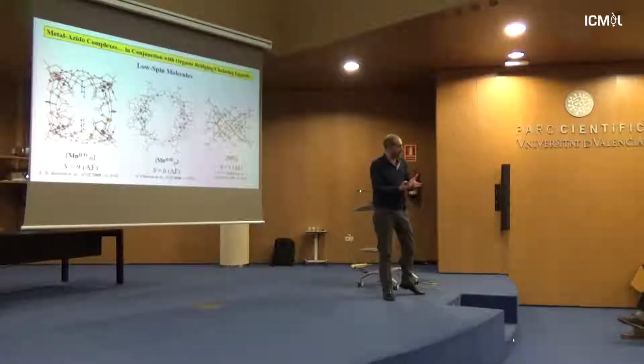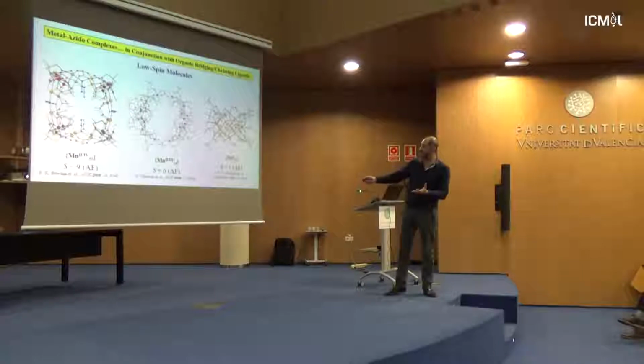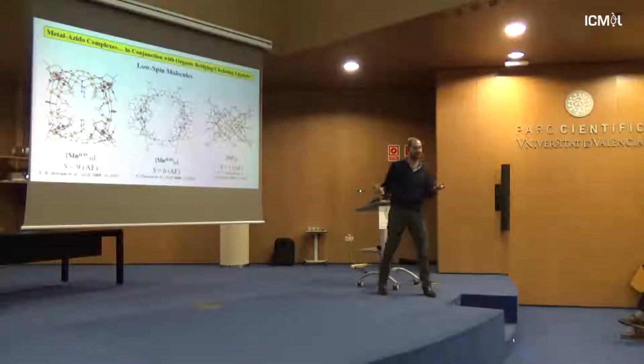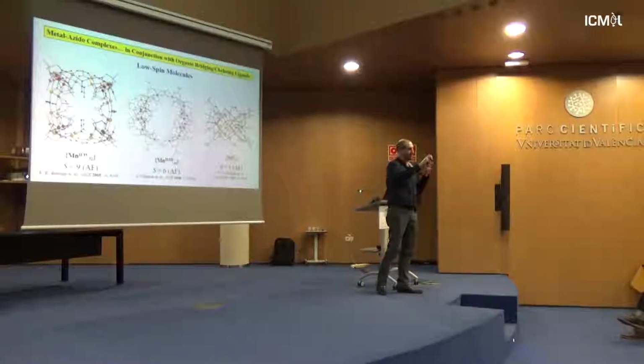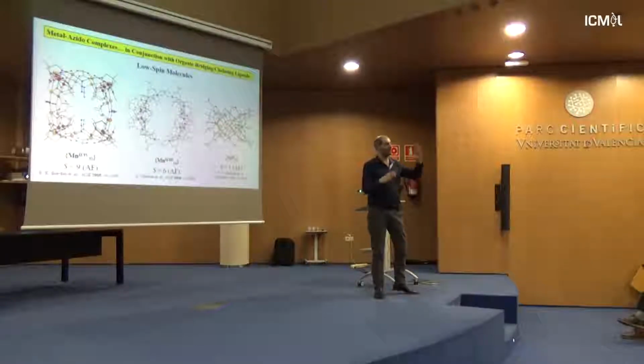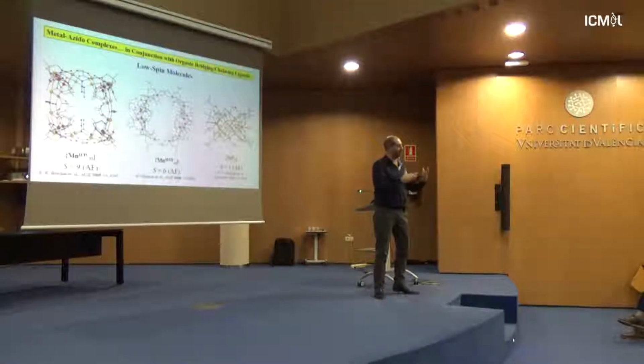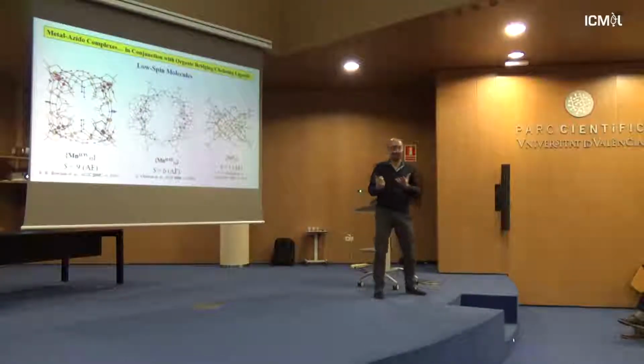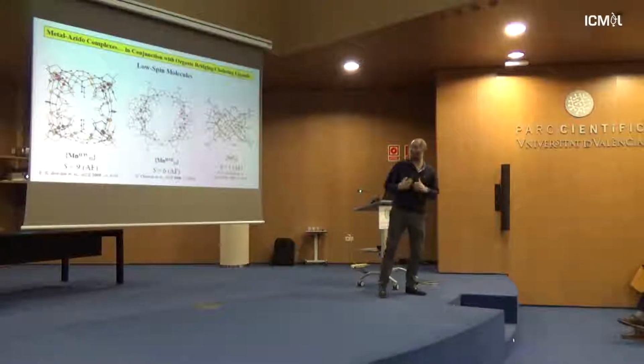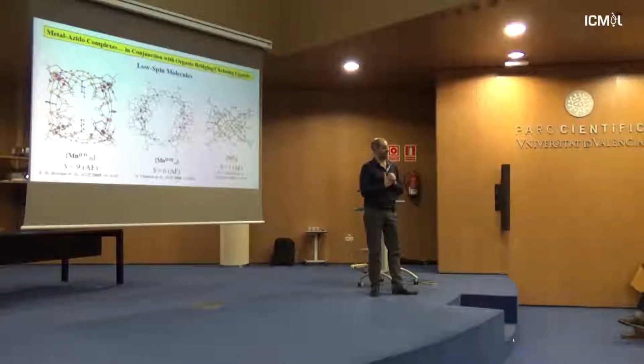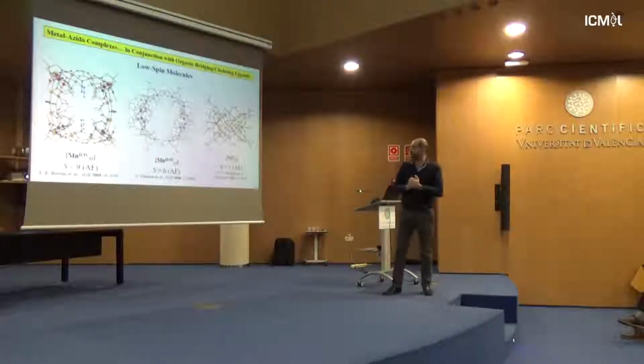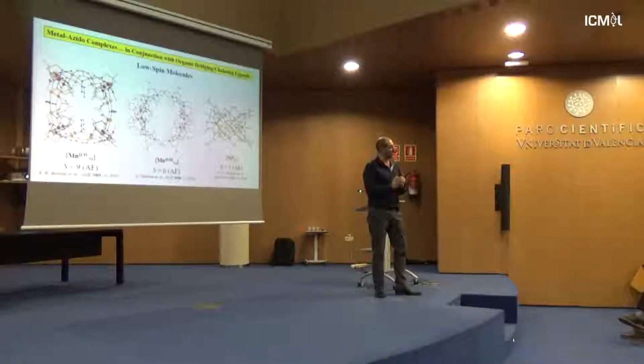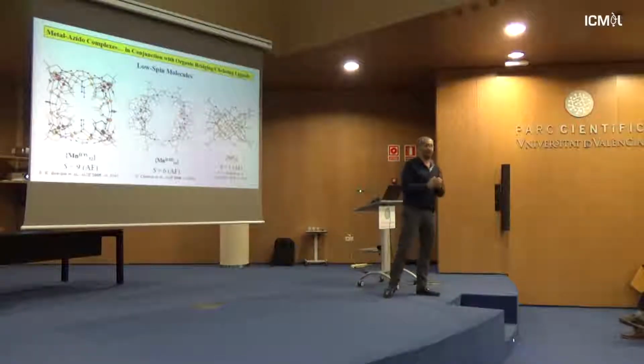Because at the same time you can get compounds of large S values, but compounds of very small S values. If you see the synthetic blend, as we call it, it is the exact same. Metals, azides, organic ligands. In the majority of the cases you also have oxides. You get cluster compounds, fantastic, but the spin is not guaranteed. And consequently, the magnetic dynamics are also not guaranteed. And this is where we started thinking a little bit about why that happens.